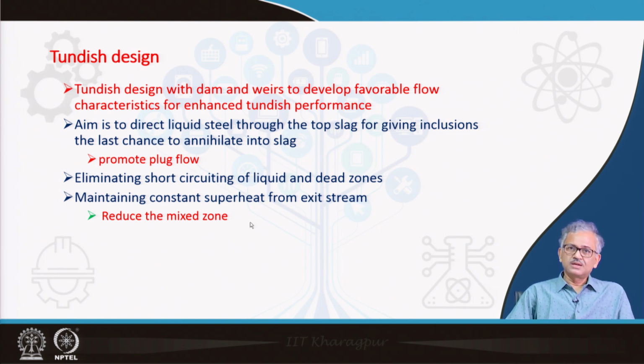So, a real reactor is a combination of plug flow reactor, CSTR, as well as a dead zone. Okay. So, this mixed reactor is not good from a constant superheat point of view, because some fluid elements can stay for a longer time, and when they come to the exit stream they will give a very low superheat liquid.